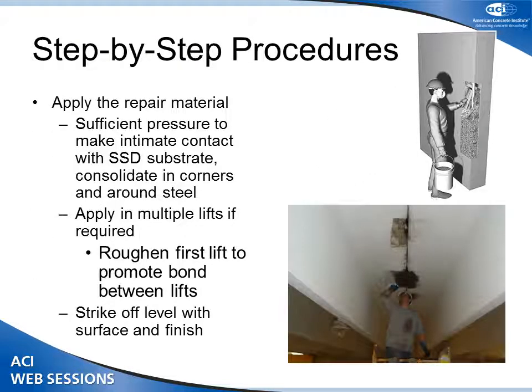And then finally, you get to the point where you're going to install the material. So you want to make sure that you're placing the mixed repair material with sufficient pressure to get good intimate contact with the saturated surface dry substrate. So you're essentially pressing the material very firmly into the surface. Many times the manufacturers will recommend scrubbing a small layer very firmly into the base and then coming with the bulk mix after that. Pay particular attention to consolidation of material around corners and around the reinforcing steel.